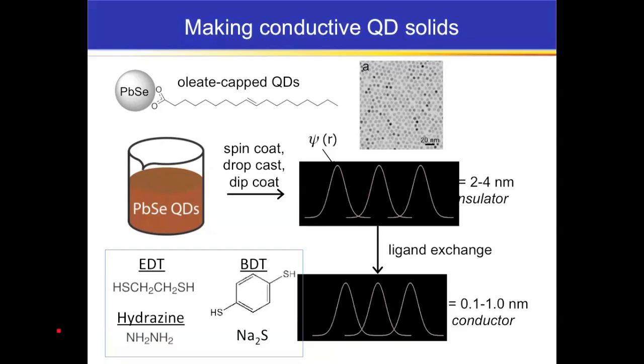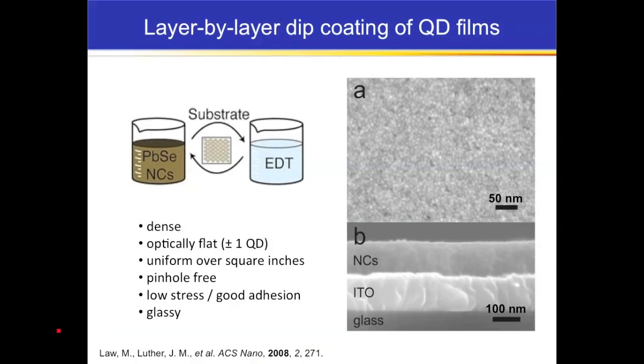So in addition to ethane dithiol, benzene dithiol, and hydrazine, people these days, the main focus in the field is moving toward inorganic ligands, such as just using sulfide as a bridge between individual quantum dots. And I'll talk about sulfide a little bit later. To actually make films for devices, what we want to do is to use layer-by-layer dip coating. And this allows us to make high-quality films that give us good yields in devices. The idea is we just take a substrate, we dip it in a solution of lead selenide, and we withdraw it. That gives us a monolayer or a submonolayer of dots, but it's covered in oleic acid.